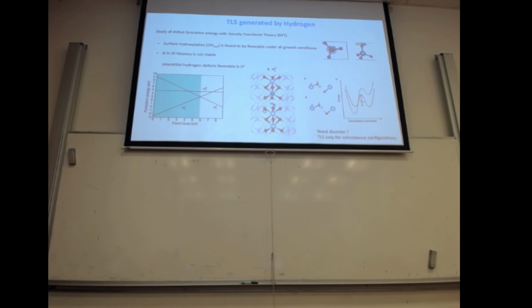And then it's H+. And now you have a problem, right? Because, okay, how does this result in a two-level system? Usually you have a configuration like that because it's interstitial, and this hydrogen loves to be attached to one oxygen. If you look at a configuration like this, where one hydrogen is very close to one oxygen, what you expect is a double-well configuration like this. And this is a two-level system that is not really a two-level system, because it cannot be excited at low temperature, since it has a huge difference in energy.